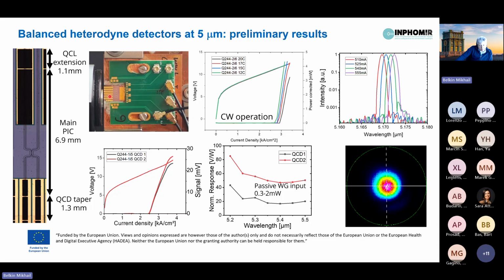In fact, it has 1, 2, 3, 4, 5, 6, maybe even 7 of these individual PICs, and we are testing them all together on the die. You have lasers, passive input also on that side, and detectors. Now the performance: we have CW operation at room temperature for the lasers with single mode emission at around 5 microns. This is the local oscillator for the balanced heterodyne detection. And then we have a 50-50 beam splitter that leads to the 2 detectors, and we could verify that the laser emission is indeed split 50-50, roughly.